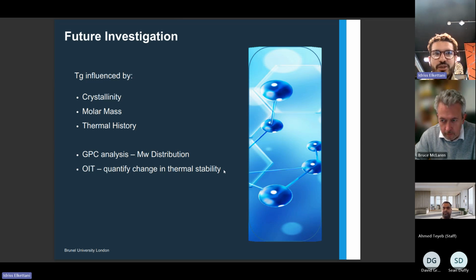A reduction in molecular weight generally means that a material is more biodegradable because it's easier for a bacteria to take it into its cell, degrade it into CO2 and water, and then spit it back out. The other thing we're quite interested to look at is the OIT, which is oxidation induction time, and that essentially gives us a nice number to pinpoint what the thermal degradation has been throughout a polymer's thermal history. So we're expecting that the ultrasound-induced components have a higher thermal degradability, but we were surprised with the TGA results, so we might be surprised with the results from the OIT as well.